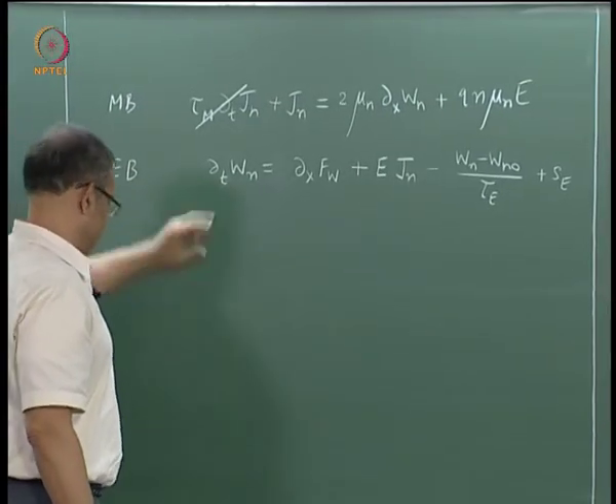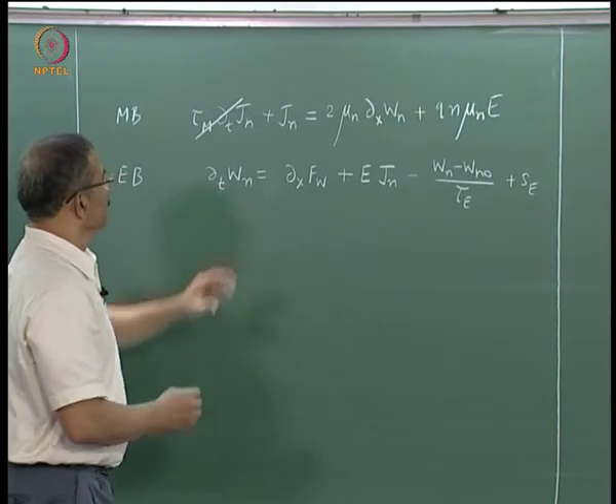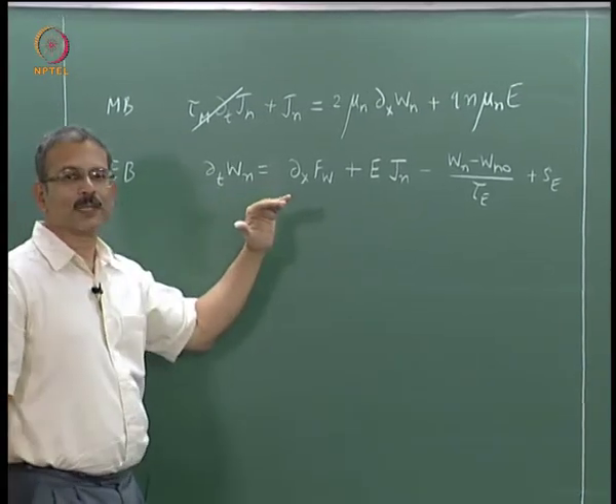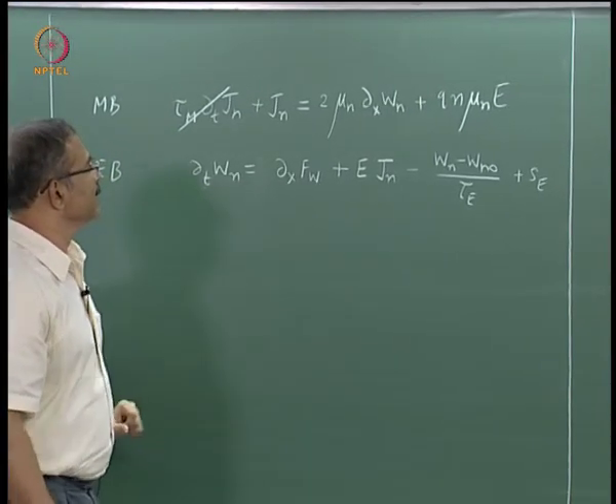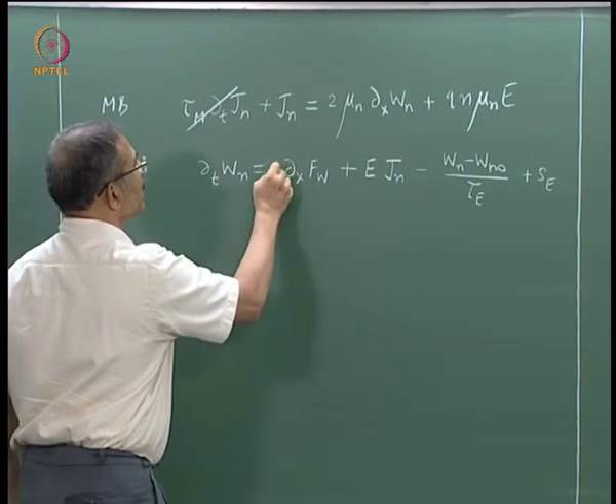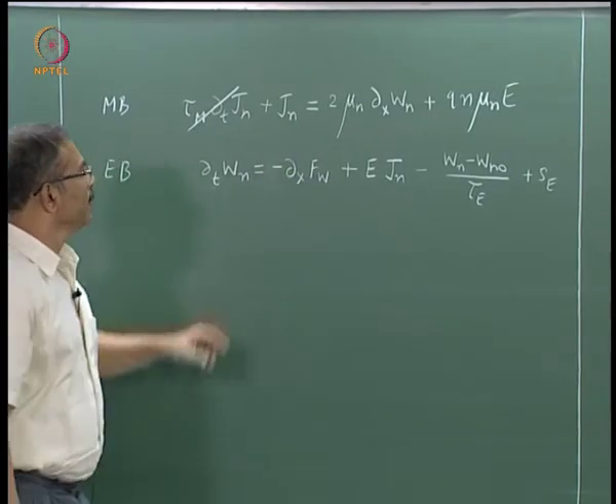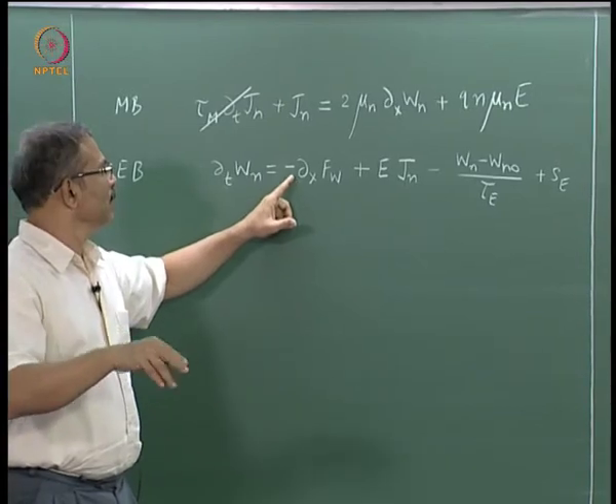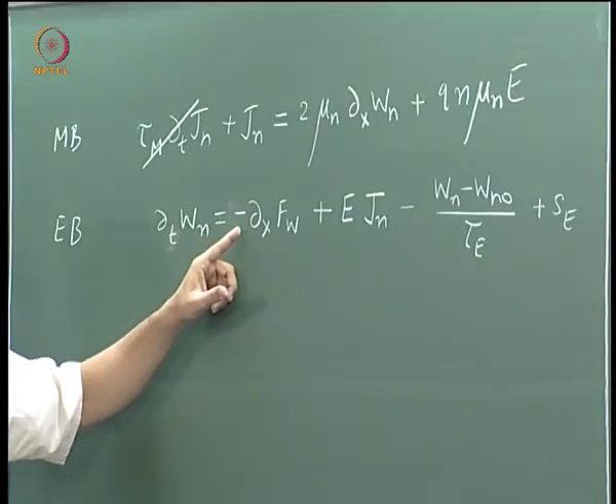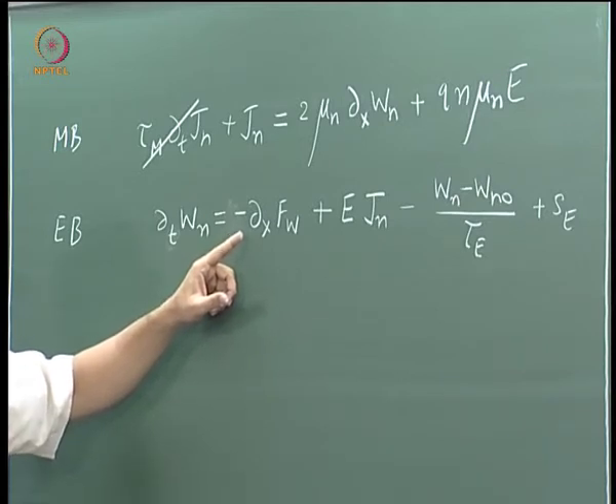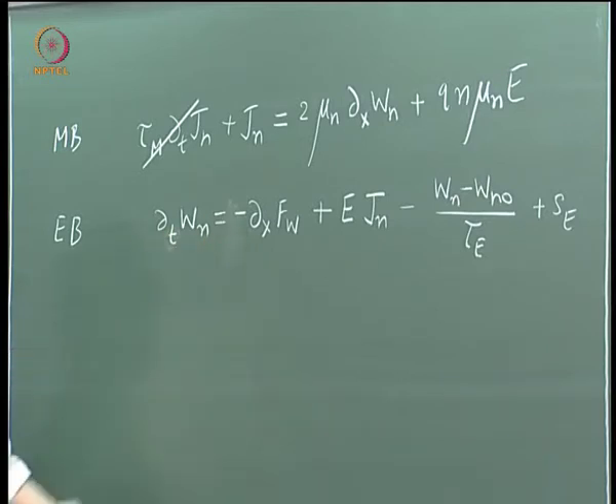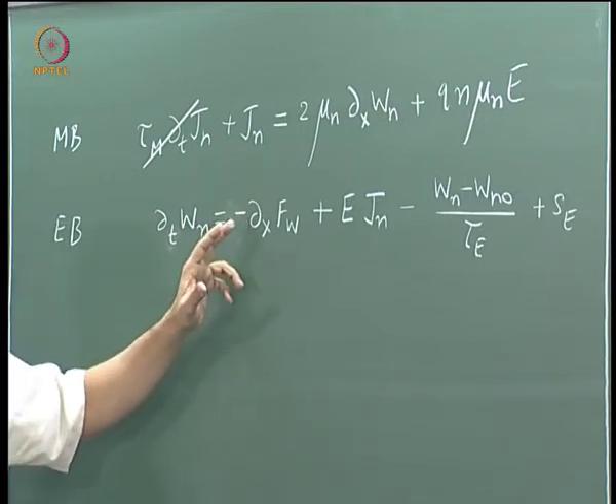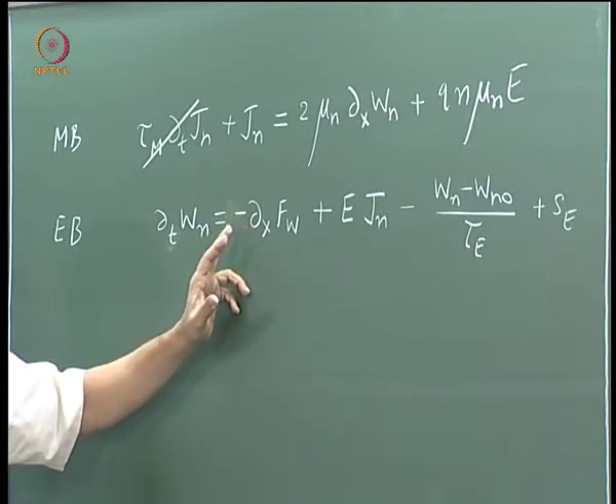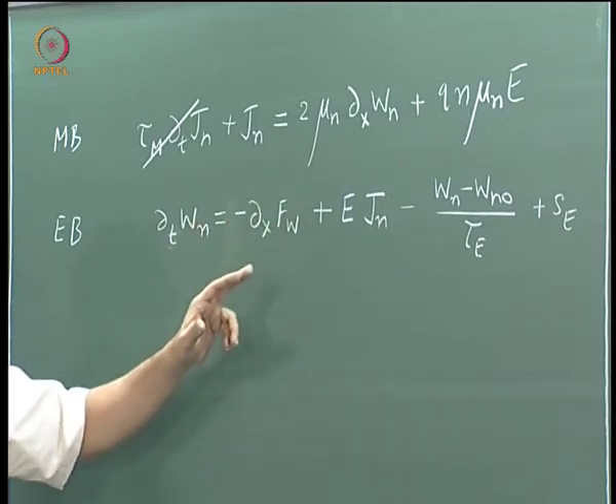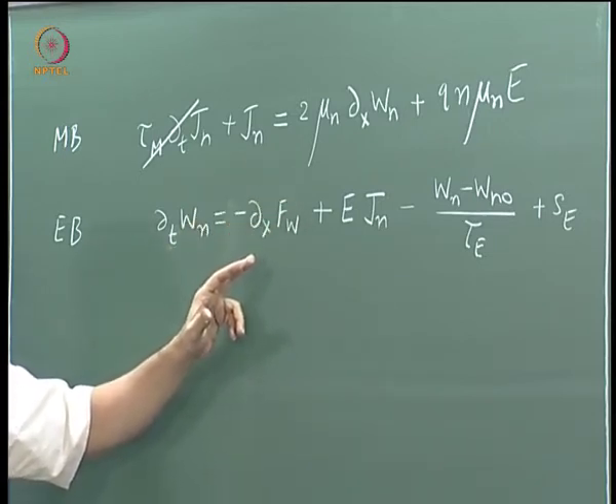Now here, before I proceed further, I wish to point out an error in this equation the way it is written. There should be a negative sign here, and this negative sign had actually been missed in the tables that I showed earlier in this lecture. So please make that correction, if you have taken down notes. However, this does not affect any of our results that we have discussed, because we have already shown that we do not use this term at all in modeling, at least the kind of modeling that we have done.